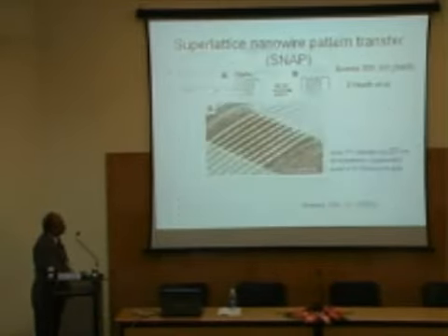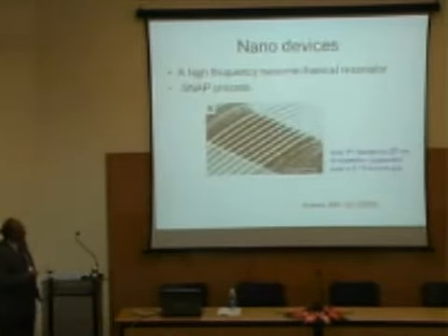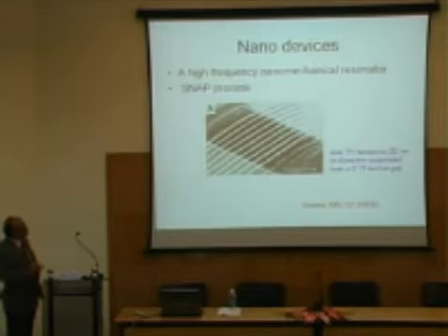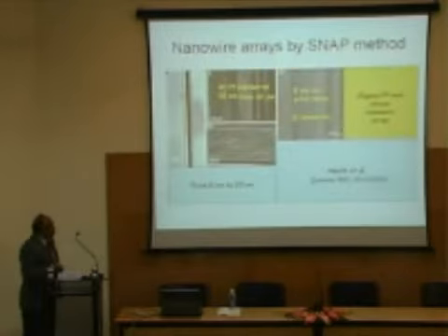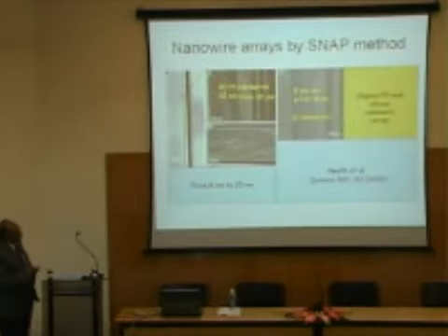interconnects. So this is a SEM picture to show you these are platinum wires made using this technique by the SNAP process, and can be used for devices. So, you have got very fine wires of around 20 nanometers in dimension, and these are very well patterned with very uniform distances in between. So, this is a real picture of that. That had only 9 wires. Now, you have several wires.